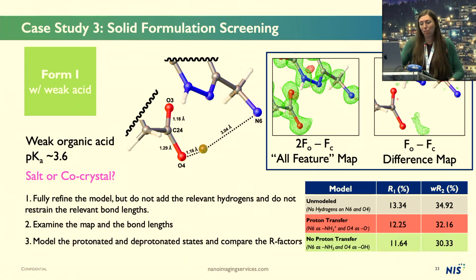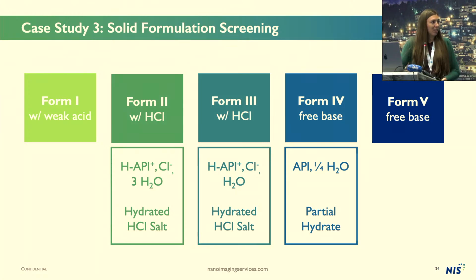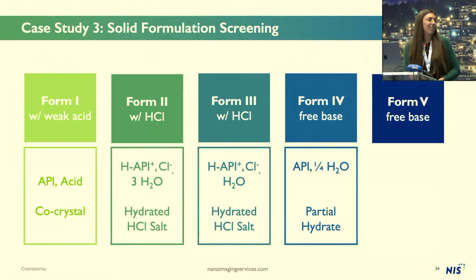So of course, we modeled all the possible locations for this hydrogen and looked at the R factors. And in this case, modeling the model of no proton transfer, so this is an OH and this is an NH2, produced the best R factors, and we concluded that this was, in fact, a co-crystal and not a salt crystal. All right, so back to our list of forms. We've now solved this form, which was a co-crystal.